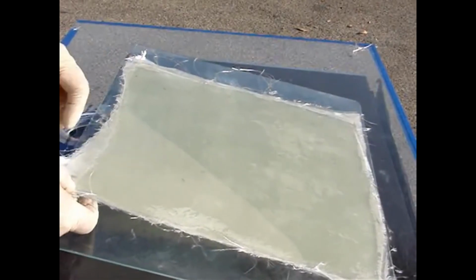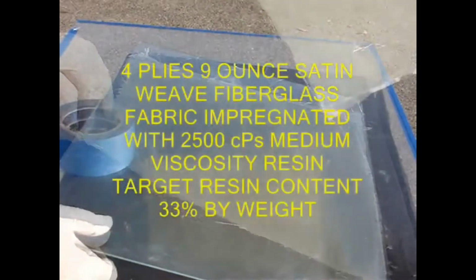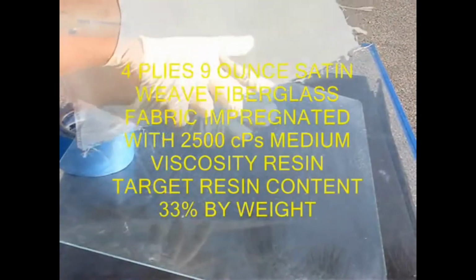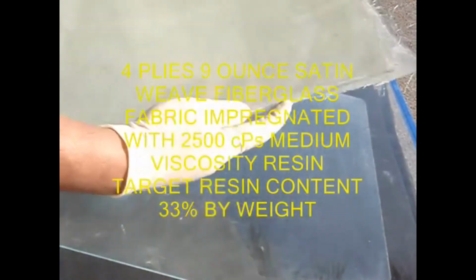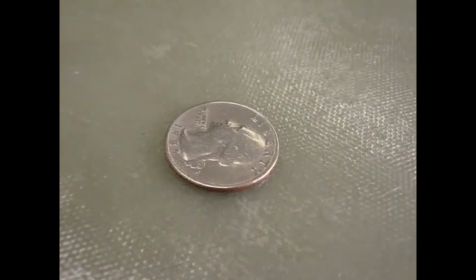This is 4 plies of 9-ounce satin weave fiberglass fabric impregnated with 2500 cps medium viscosity resin. Target resin content is 33% by weight. They are the plastic film side and also the glass cool plate side.